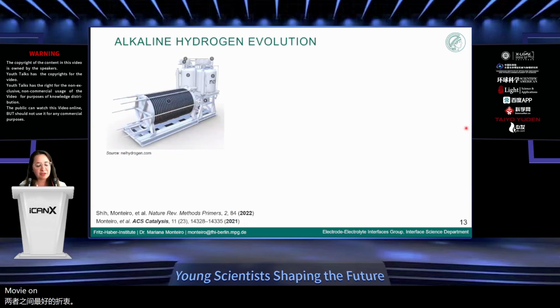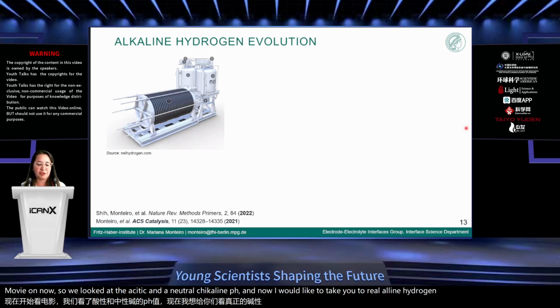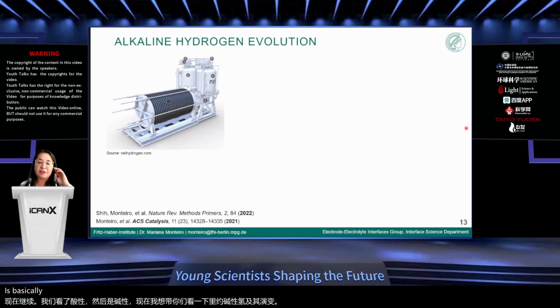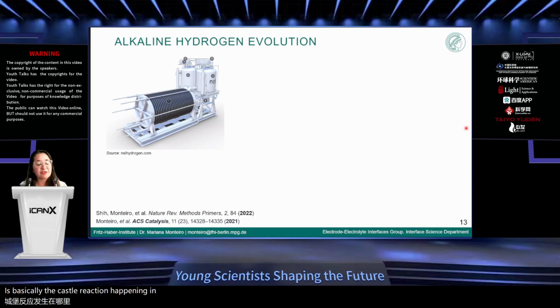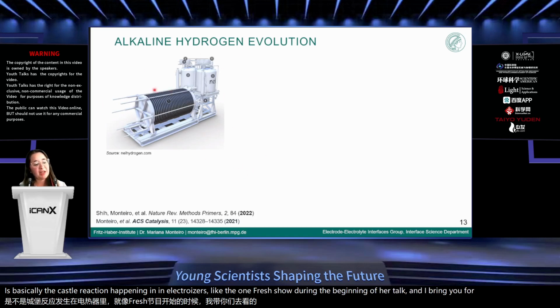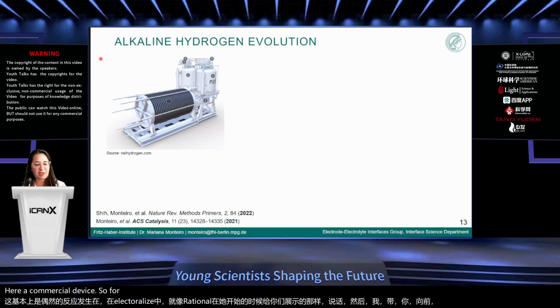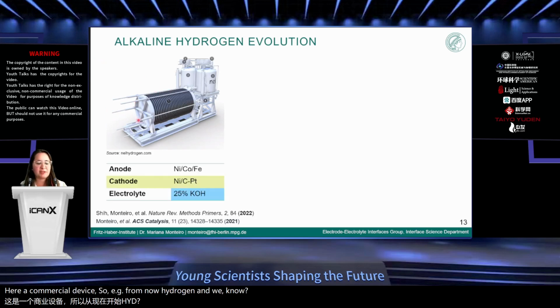Moving on now, we looked at acidic and neutral to alkaline pH, and now I would like to take you to real alkaline hydrogen evolution, which is basically the cathode reaction happening in electrolyzers like the ones Reshma showed you in the beginning of her talk. I bring you here a commercial device, for example from Nel Hydrogen. And it's accepted that in these devices, the electrodes used at the cathode are nickel and carbon-immobilized platinum. And the electrolyte that is used is very concentrated potassium hydroxide.